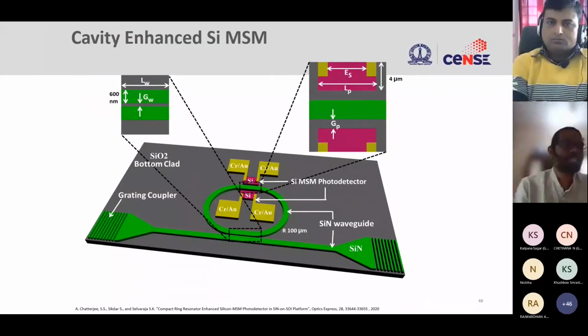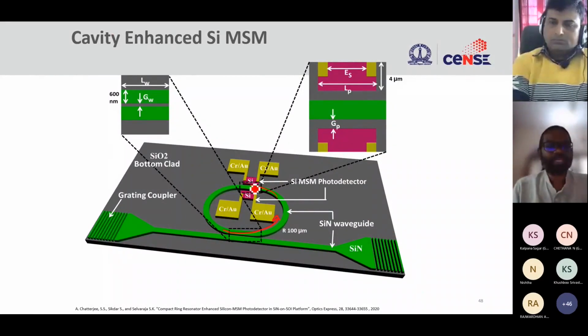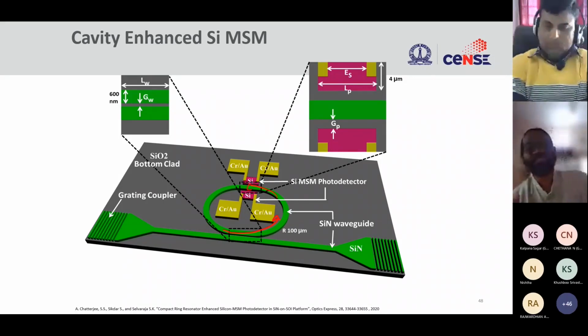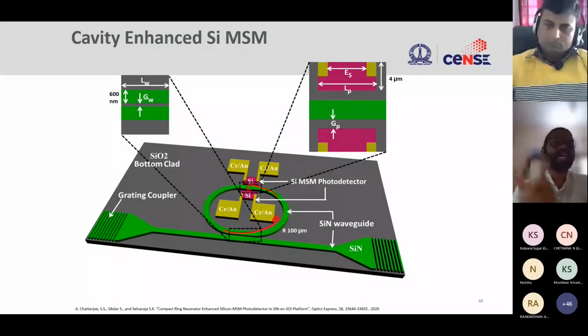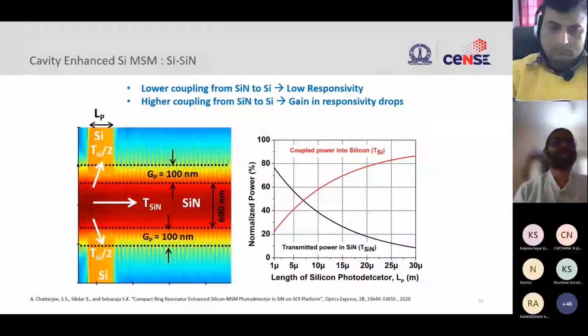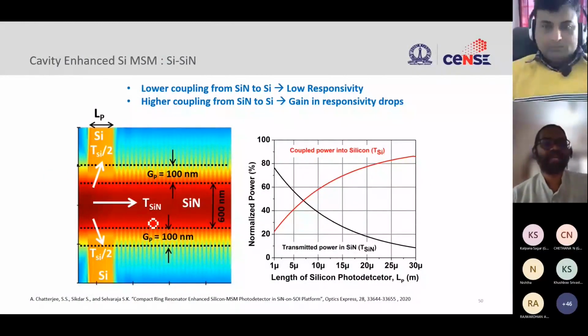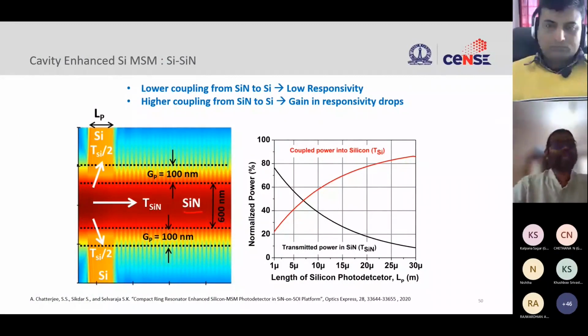So instead of just using a simple waveguide, we thought, why don't we make a cavity? So I capture the light inside this cavity, right? And then I put a detector inside this. So that means in a cavity, light is just circulating inside this cavity. So if the light is missed in the first absorption, in the second round trip it will be absorbed, right? So by doing this, we can enhance the responsivity, all right? So this is what we did. Based on the design, we had this silicon nitride as the waveguide, and we have put the silicon detectors on the sides. It's not at the bottom anymore, but it's on the sides.